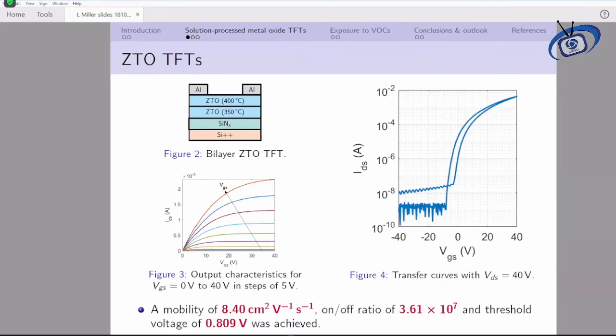I fabricated the transistors shown in Figure 2 to build on works from within my group on single layer ZTO TFTs, which I will detail shortly. A thin film transistor is a 3-terminal device consisting of a grounded source, drain, and gate. In this case, the highly doped silicon wafer shown in orange acted as the gate. The first layer of ZTO was spin coated and annealed at 350 degrees Celsius. And after 1 hour, the second layer was deposited and annealed at 400 degrees Celsius. Aluminium source and drain electrodes were then deposited on top of the semiconductor via thermal evaporation. And this is why we call it a bottom gate top contact configuration.